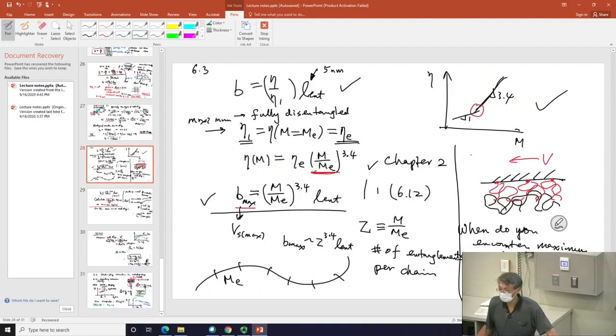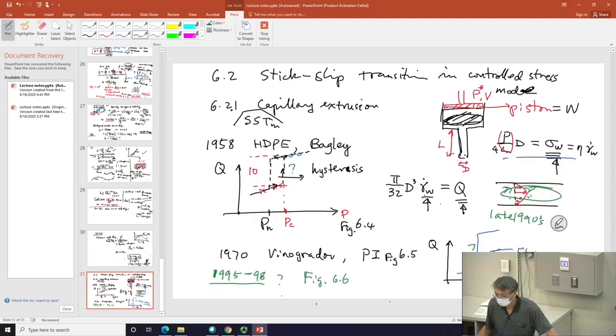so your B is negligible compared to the only thing I haven't said about any of this, which we have to do next time, is how to calculate this jump. No slip. Well, it turns out it's A times B over D, D being the diameter.